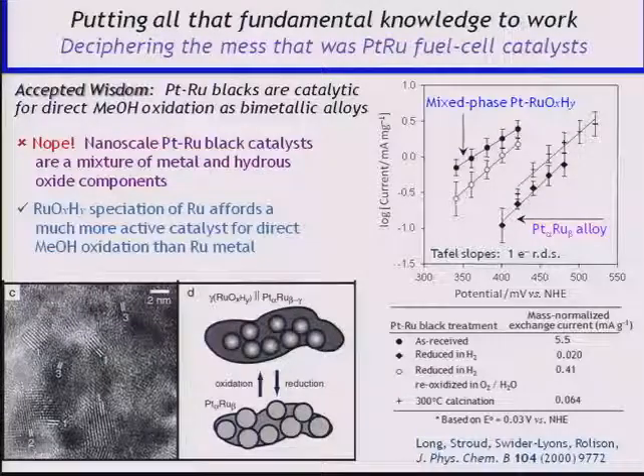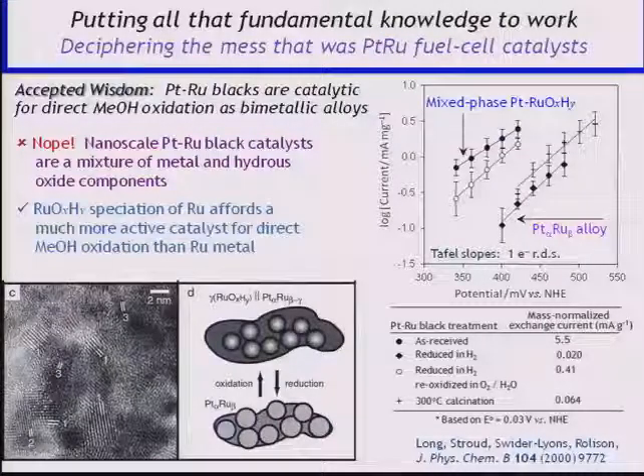So if you reduce it in hydrogen, you can indeed see lattice fringes that map onto a platinum-ruthenium alloy. We do not phase separate the HCP form of ruthenium, but once you've given it a chance for thermodynamics to do what it wants to do with a galvanic couple, you form hydrous ruthenium oxide that is laying on top of a platinum-rich inner core. It's disordered, it's got breaks in it. That's why the methanol can get down to the platinum, and the electron-proton conductivity of the ruthenia does the rest